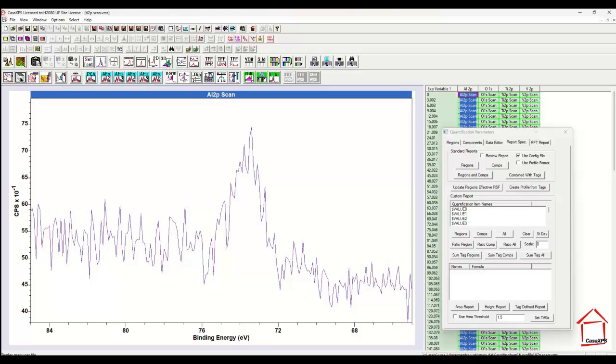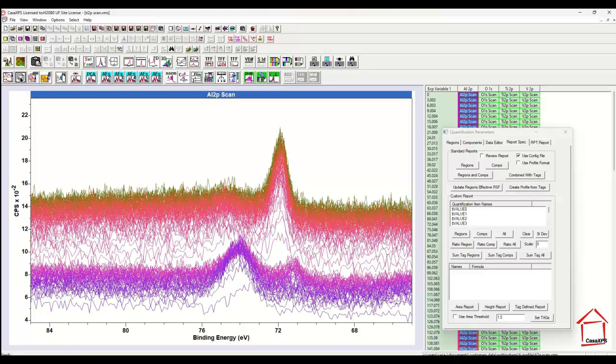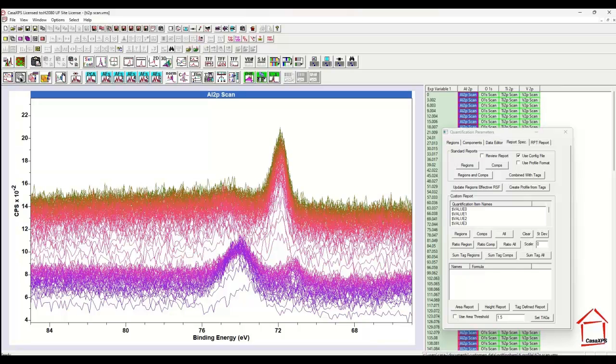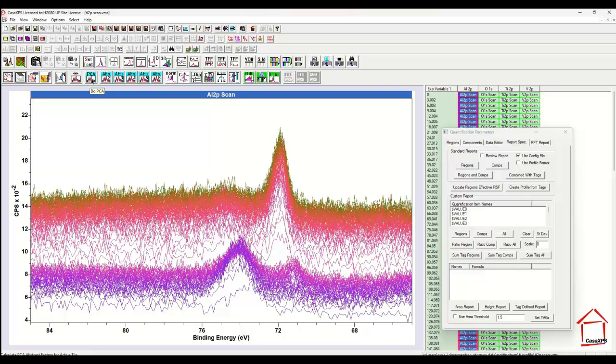And in this instance, it's just a simple case of trying to calculate from the data, not just one spectrum, which is what we were doing using the average width. But here we have a data set that is full of data and has been measured over a long period of time. So although the individual spectra are quite noisy, the sum of all these data will be quite good. And this is precisely the situation where we can use PCA and then the data can be replaced by a limited number of abstract factors that represent signal and the noise is then eliminated from the data set.